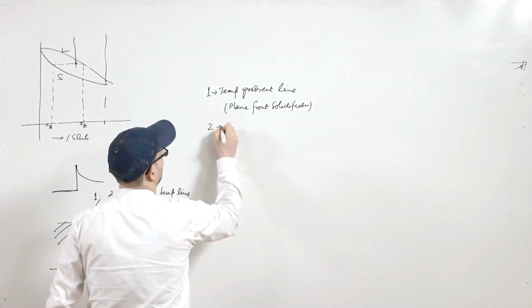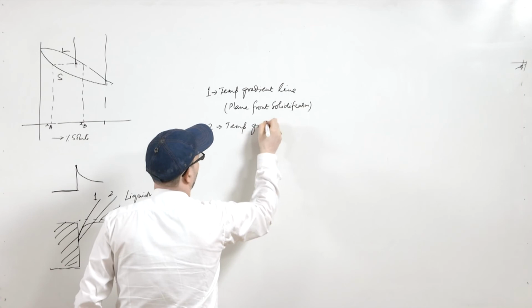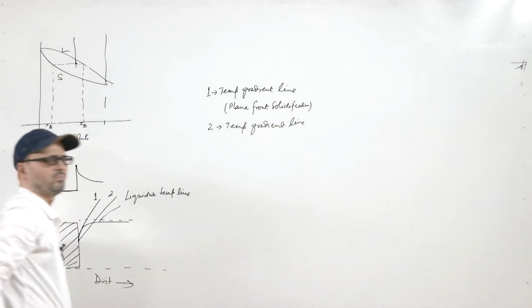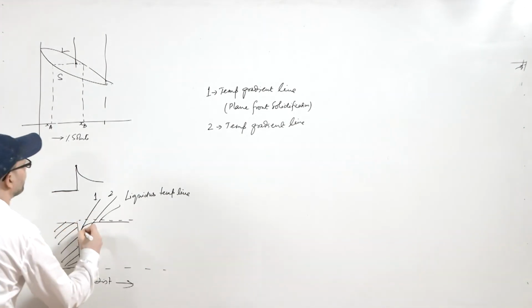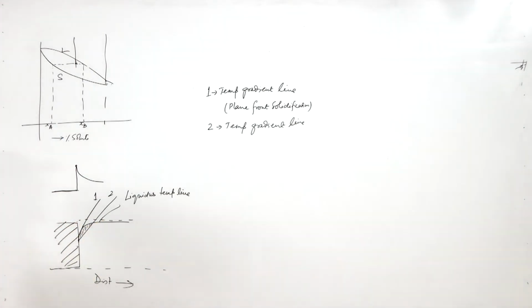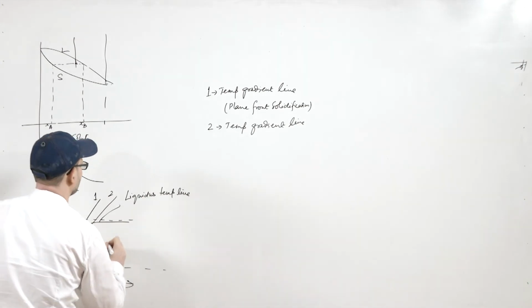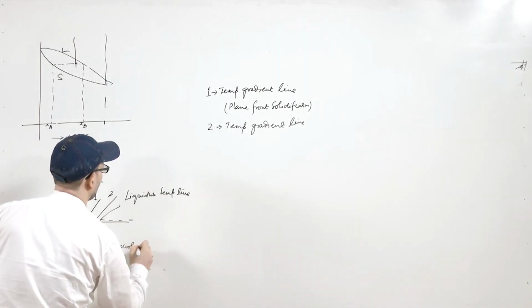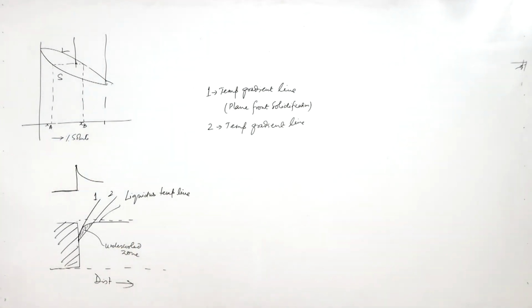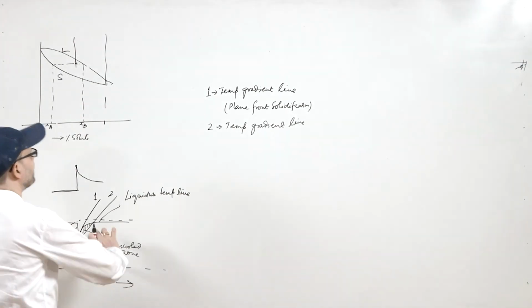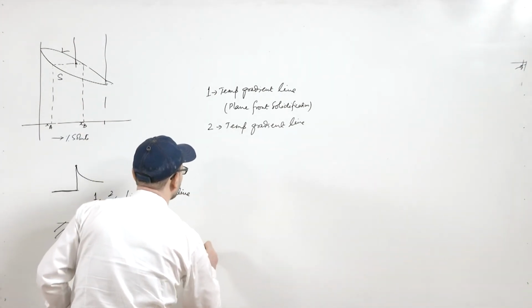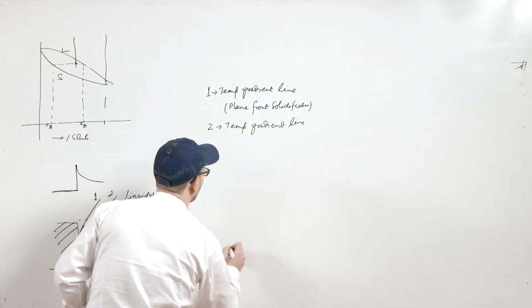If 2 is the temperature gradient line, what you see is that in the case of 2 you will have this region which has the temperature lower than the liquidus temperature, and this zone is said to be the undercooled zone. And this zone has become undercooled because of the change in the solute concentration. So, that is why this phenomenon is known as constitutional supercooling or undercooling.